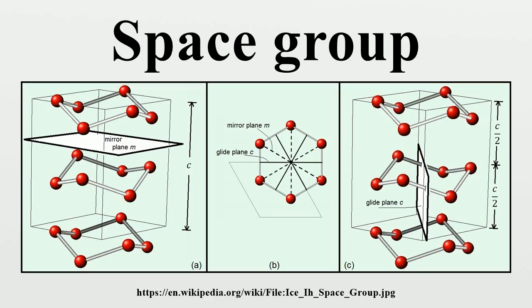By way of example, the space group of quartz is P3₁21, showing that it exhibits primitive centering of the motif, with a threefold screw axis and a twofold rotation axis. Note that it does not explicitly contain a crystal system, although this is unique to each space group. In the international short symbol the first symbol denotes the symmetry along the major axis, the second along axis of secondary importance and the third symbol the symmetry in another direction. In the trigonal case there also exists a space group P3₁12. In this space group the twofold axes are not along the A and B axes but in a direction rotated by 30 degrees. The international symbols and international short symbols for some of the space groups were changed slightly between 1935 and 2002. So several space groups have four different international symbols in use.